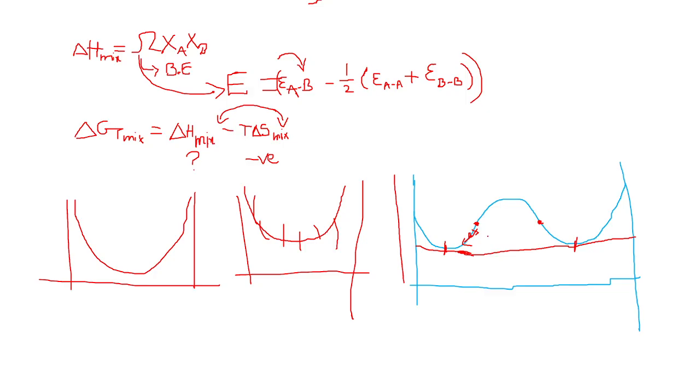So that's why if I am below this inflection point, my composition will dissociate into two parts, which have x1 and x2. Again, please keep this in mind: only one type of phase is being dissociated, right?